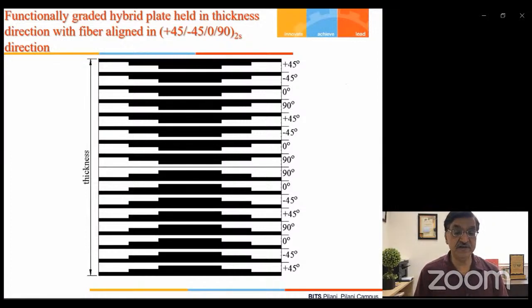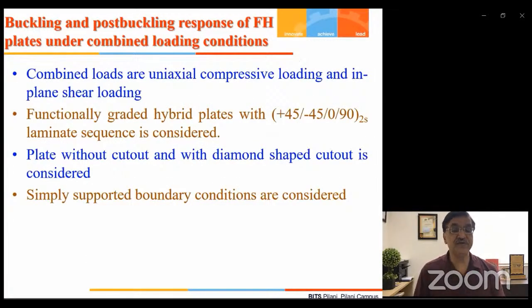You see a typical functionally graded composite laminate, with each layer of functionally graded material. The +45 or -45 represents the direction of the fiber layer in each composite, and the black represents the proportion of carbon fiber, and the white represents the proportion of glass fiber in each functionally graded composite material. So we have done the post-buckling strength under uniaxial compression load and in-plane positive and negative shear loads.